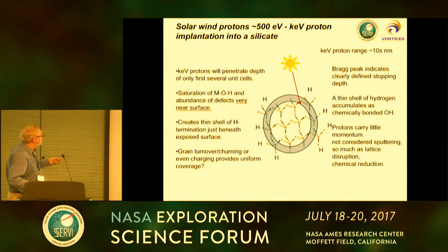This just shows you that the proton comes in, it embeds itself within the penetration depth, and this is the so-called glassy rim. It could embed itself on many particles, so we're looking at the particle interaction, but if I have a porosity, it can go deeper in and have particles beneath this. But the bottom line is what I have is I have an OH build up at the rim here, and this is what we're going to look at, and we're going to say, how is this OH changed over time?